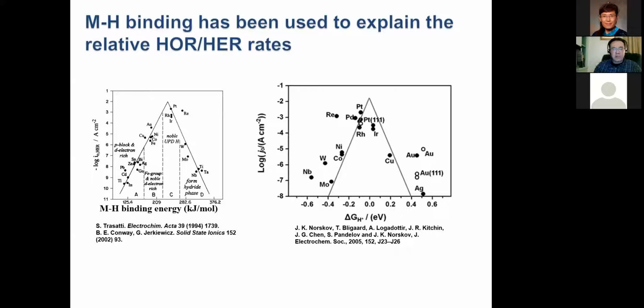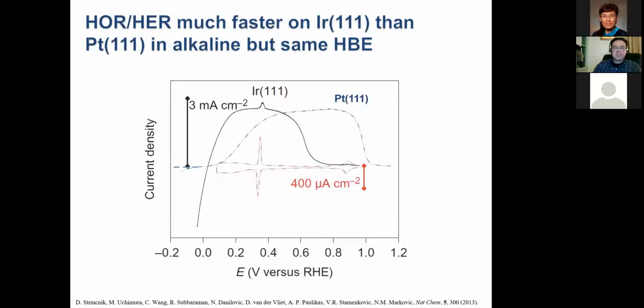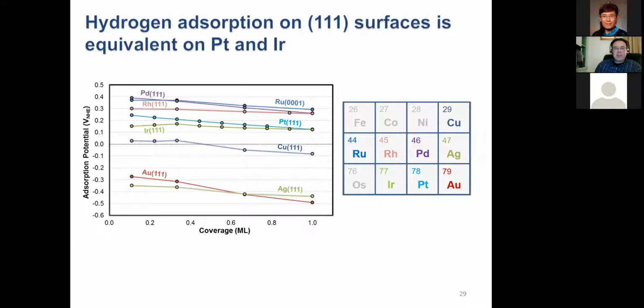So if that's what dictates the rate of hydrogen oxidation or hydrogen evolution, why should the current change? Why is there experimentally a change in the reaction rate as we move from acid to base? And here I show you results for the hydrogen oxidation or hydrogen evolution reaction run on iridium single crystals versus platinum single crystals, and what we see in alkaline. We see that there's quite a bit of difference. Actually, in alkaline, iridium is a faster, a better catalyst than platinum in base for the hydrogen oxidation reaction. And they have about the same hydrogen adsorption energy.